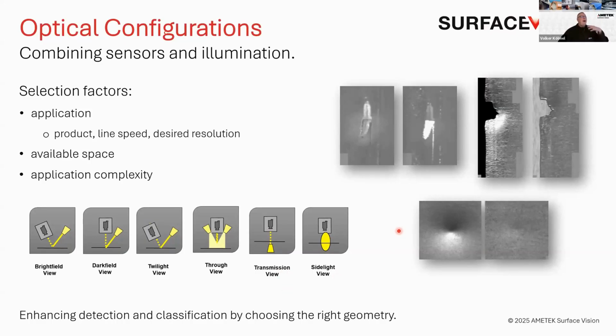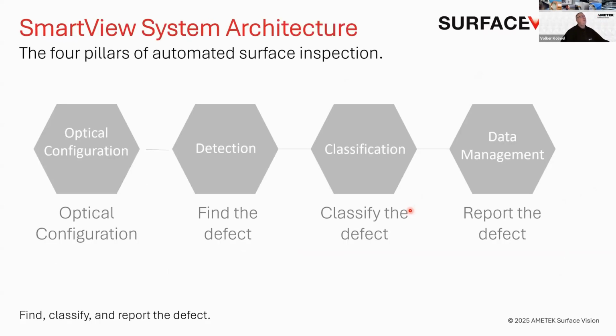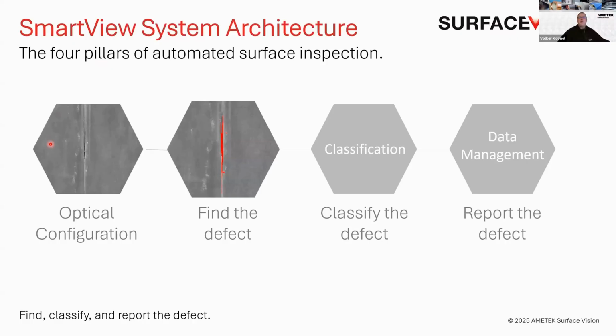So if all this is found out and tested and designed, then we have to go further into our architecture. So all the work we have done now leads us to an image where the defect versus the background should have an optimum contrast. So this is done. Now, when we have done this, we need an architecture and a software which is segmenting the defects from the background. Found a pixel of interest.